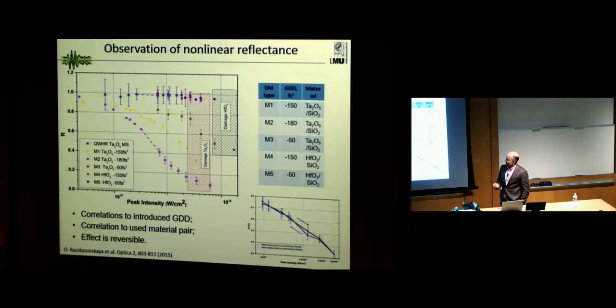not possible. And actually, when I remeasured these mirrors with my spectrophotometer, I still got 100%, but he goes to his setup and gets 10%. We tried to look for the problem, and actually the problem is the intensity of our light. The violet color shows how the reflectivity of the mirrors changes with intensity. And you see, when we increase the intensity, the reflection drops, and it goes to 10%, and the very funny thing is that these mirrors remain standing for a long time, they can stand for an hour with a reflection of 10% and not be damaged. It means if we reduce intensity, which is shown on the graph here, it's basically the same. We just increase intensity and decrease intensity. It means the mirror's reflectance just depends on intensity without any visible damage.